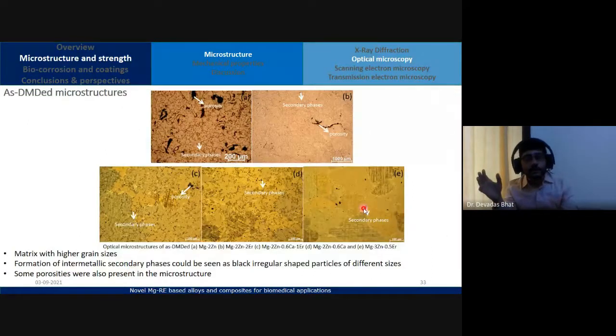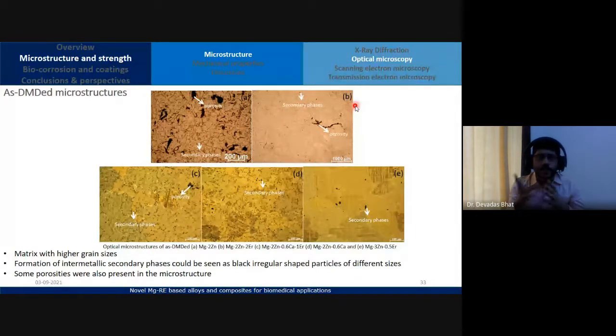Then we do the optical microscopy. The etchant that we have used here is acetic picral. Acetic picral is a combination of picric acid and acetic acid, with some distilled water and pure ethanol. The recipe is available in the ASTM standard, which works excellently for such alloys. For the as-DMD microstructure, we have observed a very large grain size. We have seen certain porosities. We could see certain secondary phases that are very large in size.